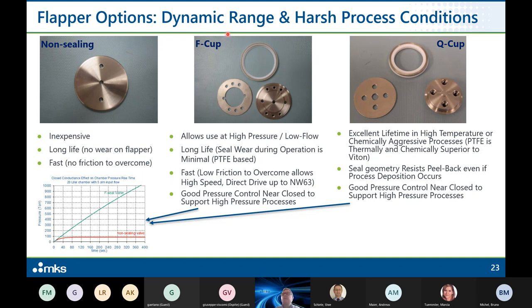An improvement for us is the F-cup, which is not a solid O-ring. So it's a structure which allows us to get less friction, so we could use this for high-speed valves and with direct drive, so not extremely high torque is required. It will have a long life, it's PTFE based, so it is also good for most of the process gases.